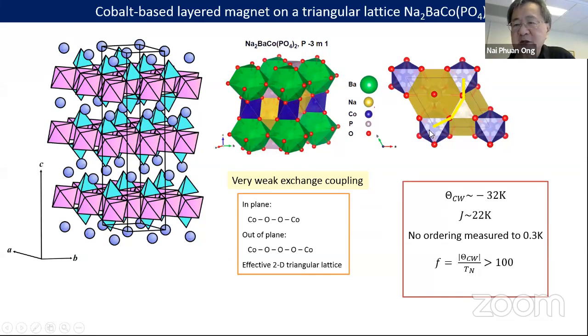But the cobalt exchange is mediated by a super exchange, right? It's going through two oxygen atoms, as shown by this yellow line. So the exchange is very weak. So this system is almost paramagnetic, but it orders. In zero field, it orders. And sorry, I said it wrong. It doesn't order even down to 300 millikelvin. So it's always frustrated.